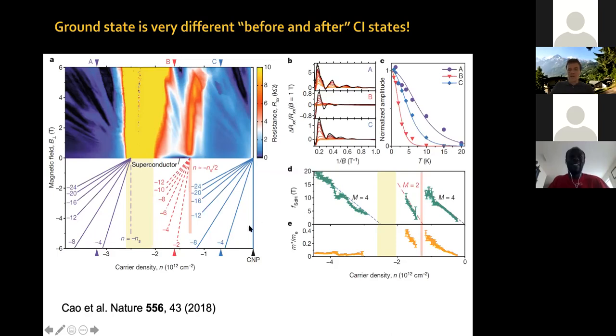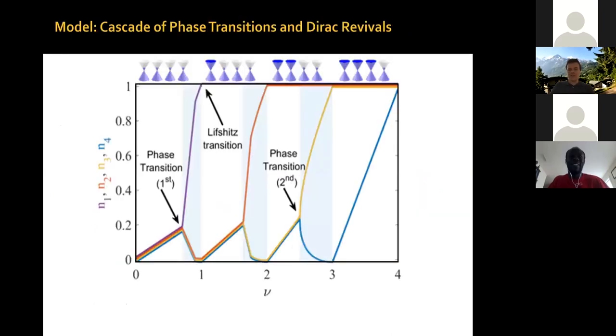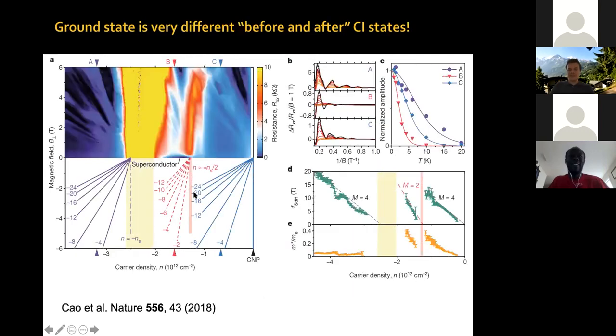Now, this is much easier to explain, okay, because as you can see here, after filling factor 2, a similar story happens for -2. Two flavors are occupied, and you have two flavors unoccupied. So you now have degeneracy of 2 in your Landau levels. You have degeneracy of 4 at the beginning. You have degeneracy of 2 after filling factor 2, okay? So that explains this loss of degeneracy in your Landau fan diagram that we already observed in our initial experiments, okay?